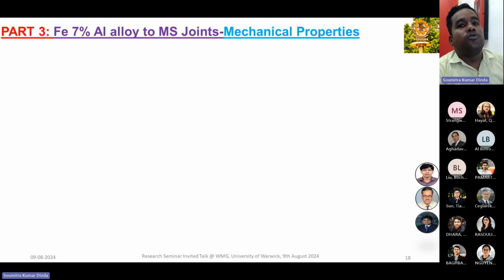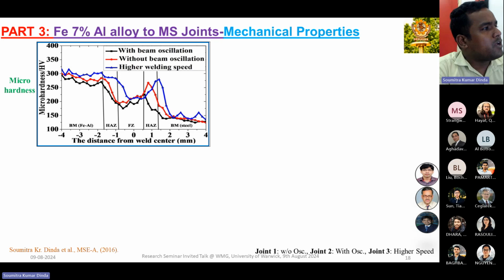And then we move to the mechanical properties. So we have the defect background, then we do the mechanical property. Mechanical property means we did the micro hardness. In case of micro hardness, we just see the hardness difference in both HAZ regions because of the grain size change from the weld zone to the base metal side. That's why the hardness is changing. But in other cases, we see a similar trend of hardness for all three conditions.